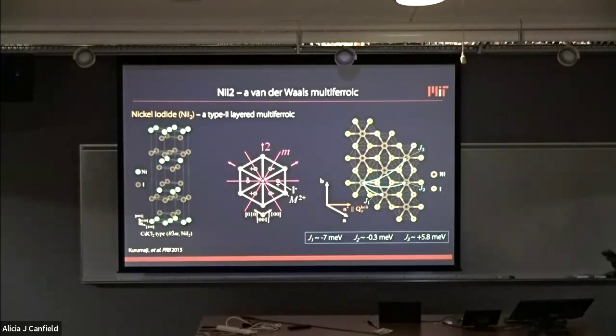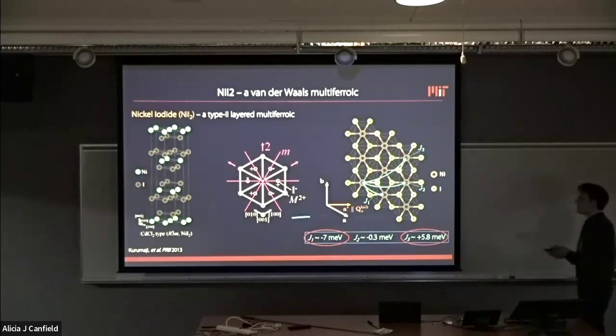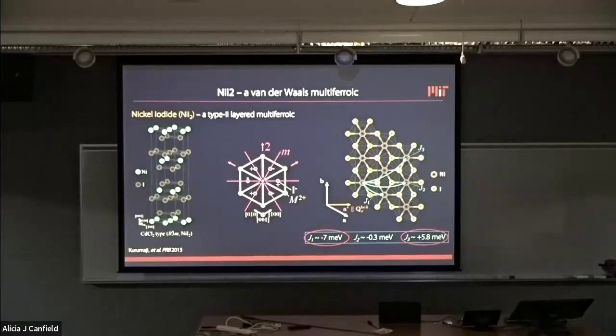There are 3 dominant exchange interactions in the triangular lattice, at least for the case of nickel. There's the first nearest neighbor exchange, the second nearest neighbor exchange, and the third nearest neighbor exchange. But the first and the third nearest neighbor exchange are really the ones that have the largest superexchange constants. Nearest neighbor tends to promote ferromagnetic order, and third nearest neighbor tends to promote antiferromagnetic. So the system does something in between, which is it finds a non-collinear ground state. This very much sets the stage for the realization of the non-collinear frustrated state.